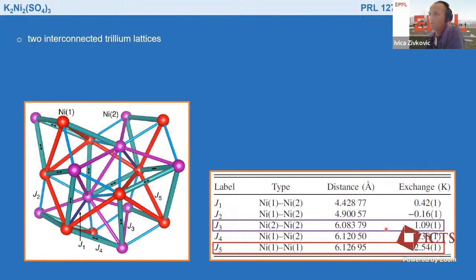Okay, so that was the majority of the experimental part, and now from the conceptual point of view, these two interconnected trillium lattices, how are they interconnected? So from the DFT calculations, these exchange interactions have been extracted, and you have 5 of them. So this is a rather complicated network.